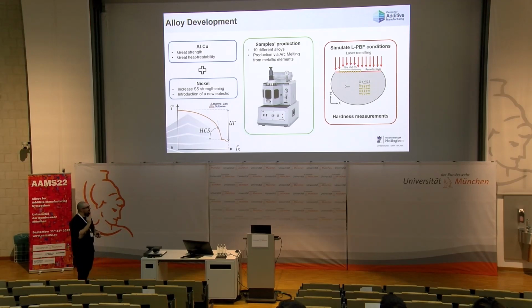And here you need to be very precise to go spot on the melt pool and not put the indents between the melt pool and the core, so that we are 100% sure that these are the properties found in the remelted microstructure.